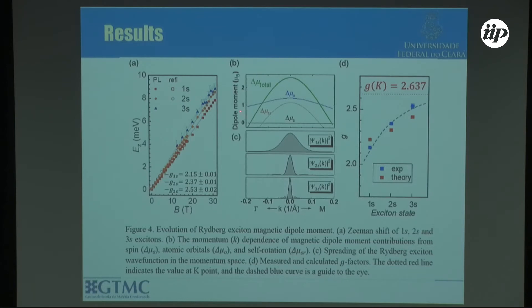When I do the full calculation, I get G-factors for 1s, 2s, and 3s states that are consistently increasing — which is exactly what was observed in the experiment, where the Zeeman shifts for 1s, 2s, and 3s have different and consistently increasing values, repeated many times in the lab.